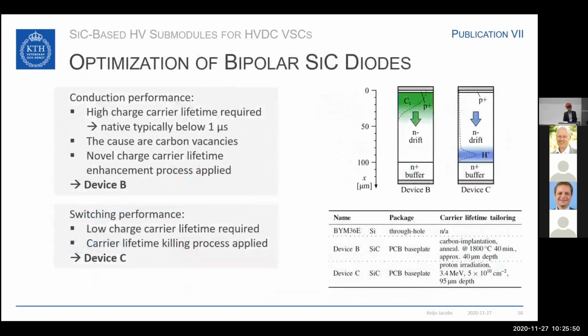For this converter, we investigated the performance with differently optimized silicon carbide diodes. Those diodes have a blocking voltage of 10 kilovolts, and you can either optimize them for conduction or for switching performance. For conduction performance, a high carrier lifetime is required. Natively, that is below 1 microsecond, and the cause for this low charge carrier lifetime are the carbon vacancies in